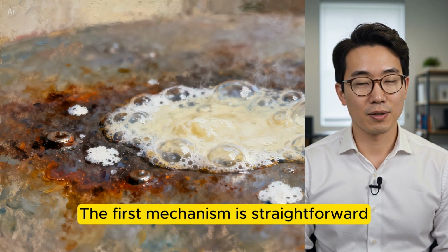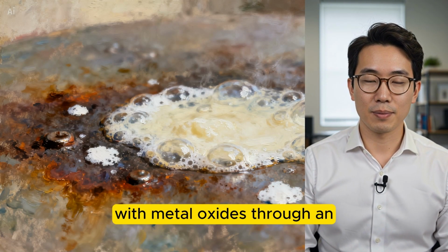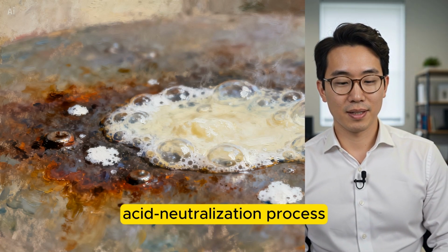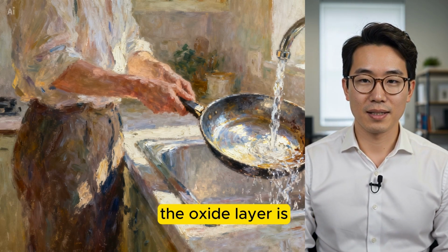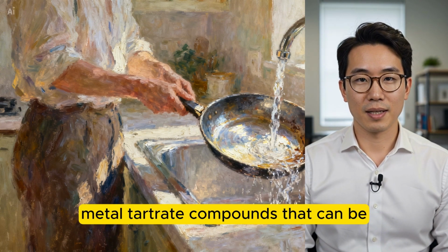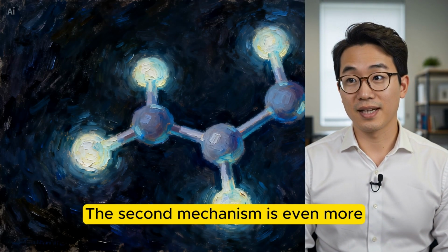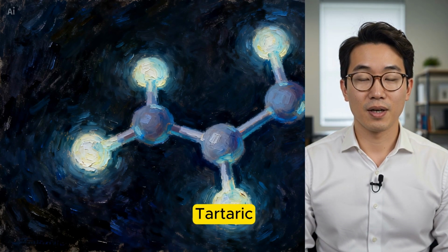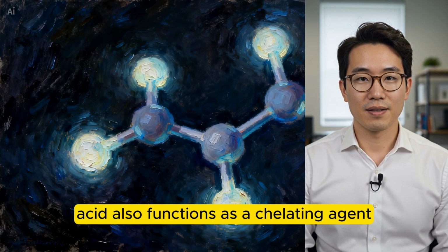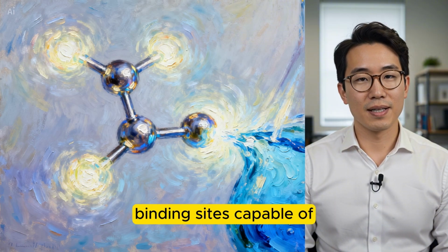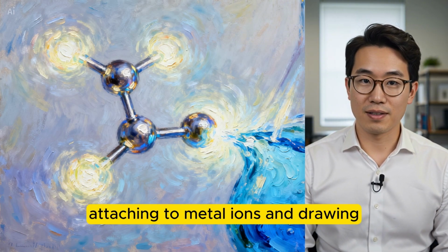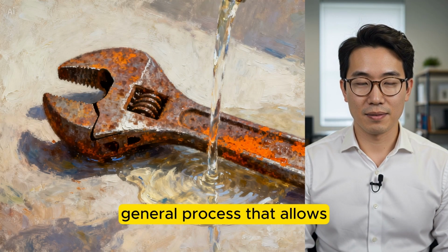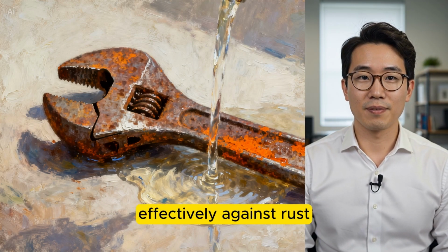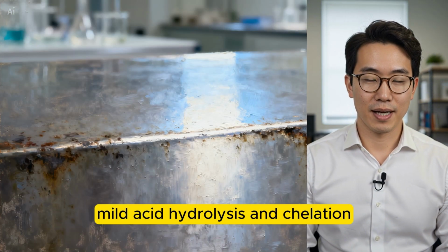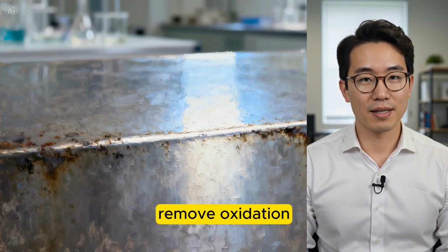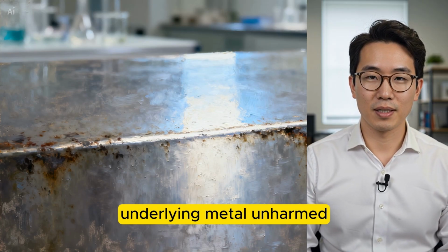The first mechanism is straightforward. The weak acid reacts directly with metal oxides through an acid neutralization process. As that reaction occurs, the oxide layer is converted into soluble metal tartrate compounds that can be washed away with water. The second mechanism is even more important. Tartaric acid also functions as a chelating agent. Its molecular structure contains multiple oxygen-binding sites capable of attaching to metal ions and drawing them into solution. This is the same general process that allows citric acid to perform effectively against rust. Together, mild acid hydrolysis and chelation remove oxidation cleanly while leaving the underlying metal unharmed.